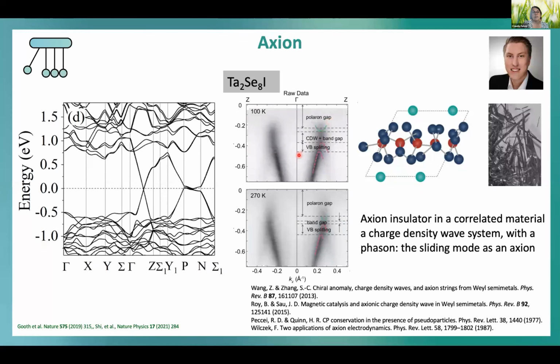So we were first a little bit frustrated, but then we found a series of interesting papers which said if you find a charge density wave instability in a Weyl semimetal, you see a quasi-particle excitation for an axionic charge. An axion is a particle which is looked for in explaining dark matter in the universe, and was not yet seen. So this was extremely exciting, but then it also changed how to find out what to do to see whether this compound is really an axion insulator, and not simply a simple insulator.